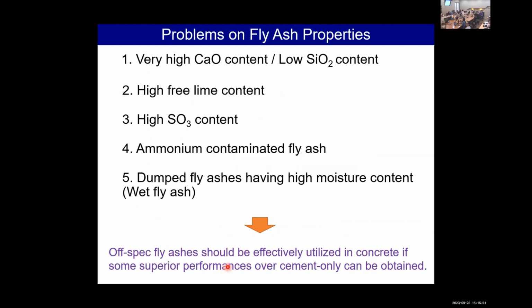The problems on the fly ash properties are very high calcium oxide or low silicon dioxide content, high free lime content, high sulfur trioxide content, ammonium contaminated fly ash, and the last one is damp fly ash having high moisture content, or what we can call wet fly ash.